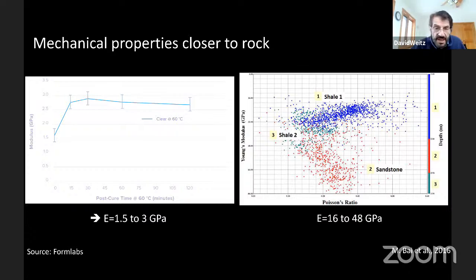And what's interesting is if you look, and I apologize for the size of this, but I'm going to tell you what these said. If you look at the modulus, this is the Young's modulus here for various kinds of samples that you actually do fracking with. You see that it's of the order of 30 or 40 gigapascals. The sample that we're using, the modulus depends on how you cure it. After you print it, you have to cure it at a higher temperature, but it's of the order of a few gigapascals. Here's 1.5 and here's 3.